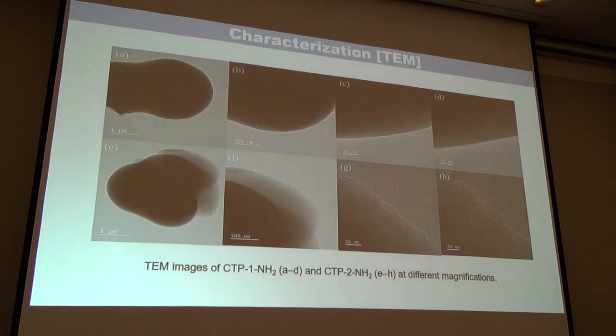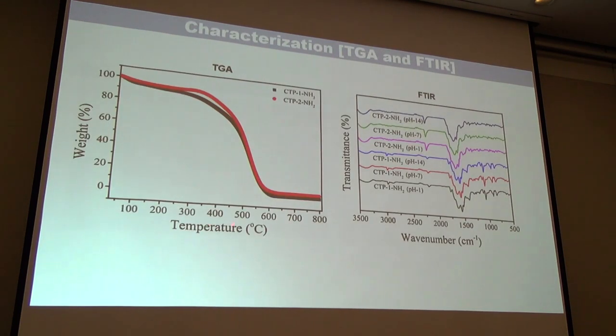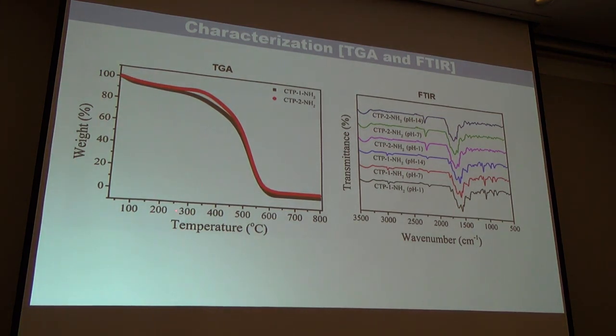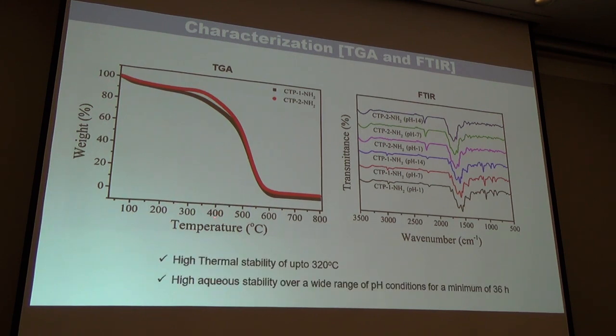Further, the TEM analysis of the material suggests that these two materials have a high degree of microporosity, which is in good agreement with the nitrogen adsorption desorption isotherm. Further, we have tested the thermal stability of the material using TGA. We can see that the material is stable up to 320 degrees centigrade. The chemical stability is analyzed by treating the CTP1 and CTP2 materials in aqueous medium at different pH conditions, such as pH 1, 7, and 14. After 36 hours, we tested the FTIR, and it shows there is no change in the peak position and the intensity, which suggests that the material is very much stable under these pH conditions.